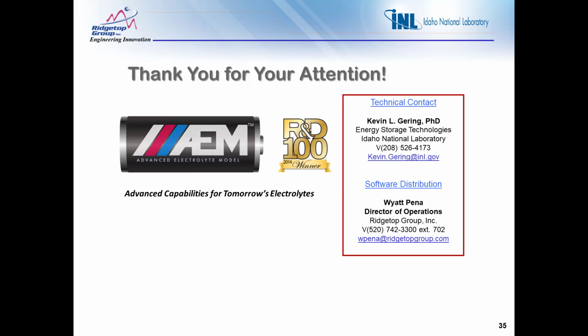And so what we've learned is that we do design with AEM. We formulate the fundamental electrolyte composition. We test that in cells and check for compatibility. So if we're seeing good compatibility, we'll see a fairly low aging rate, say over the first 150 to 200 cycles. And if there are any inconsistencies or incompatibilities between the materials, that generally should show up early, even during the formation cycling, which is very, very early in the cell life.